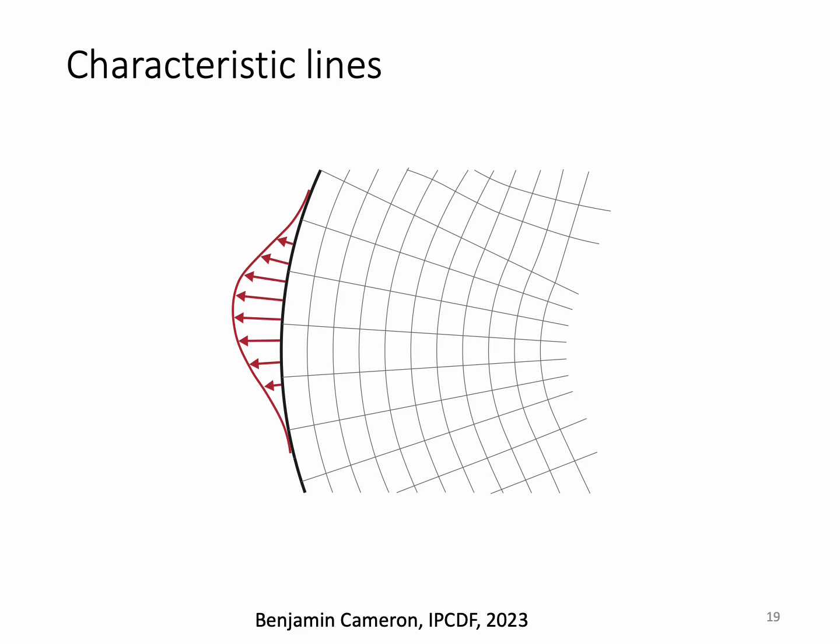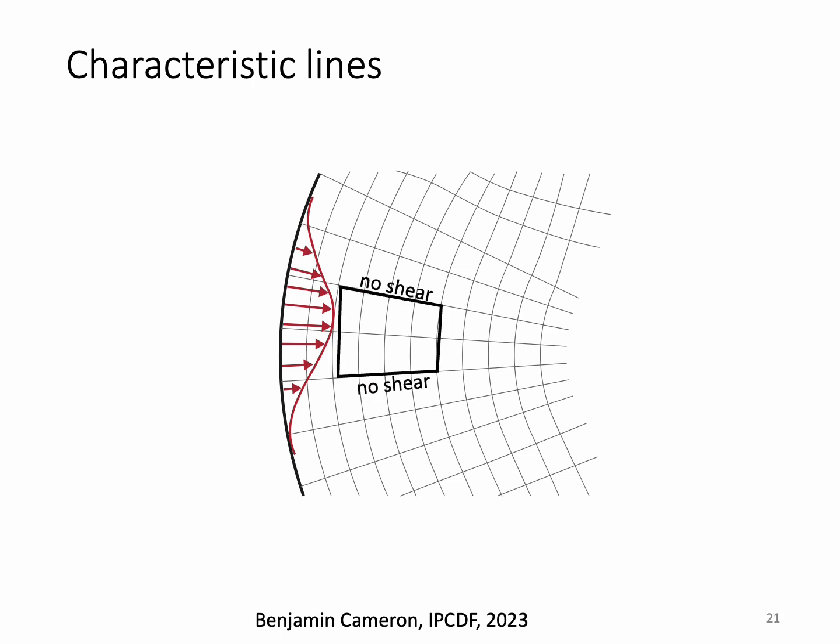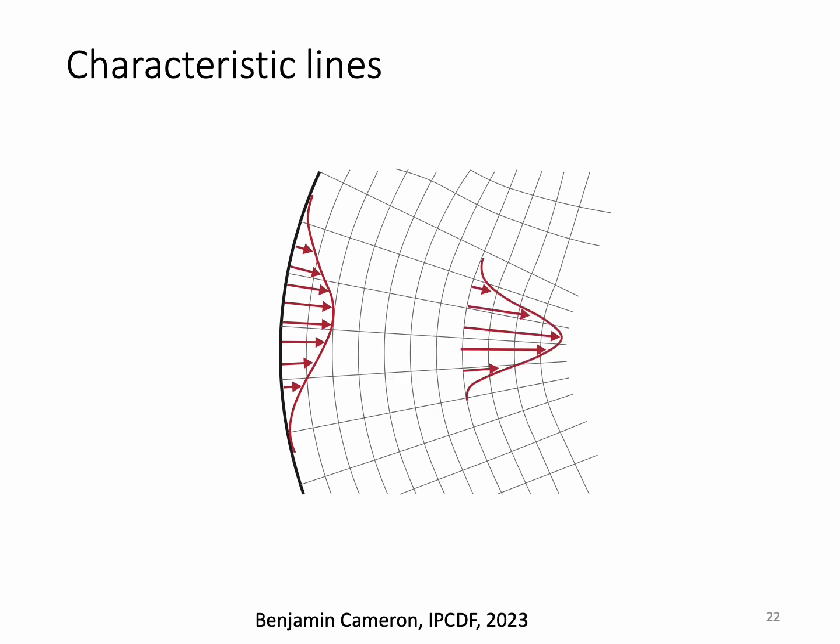Also, we have traction boundary conditions, which is the red curve on the left-hand side. And so the material is getting pulled. For each action, there's an equal and opposite reaction. We can imagine an area of material here, subject to this force. No shear can act across these boundaries. So as the area gets smaller, the stress gets amplified. So you can follow these lines in a directional way and calculate the stress as you go.